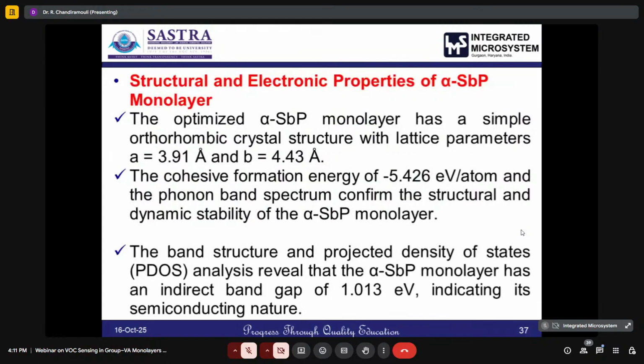First of all, we studied the structural stability of alpha SbP. The optimized alpha SbP monolayer shows an orthorhombic crystal structure with a lattice parameter a of 3.91 angstrom and b of 4.43 angstrom. The cohesive formation energy, which ensures static structural stability, is minus 5.426 electron volt per atom. For dynamic stability, we also explored the phonon band spectrum, where no negative frequencies are noticed, which shows the dynamic stability of the alpha SbP monolayer.